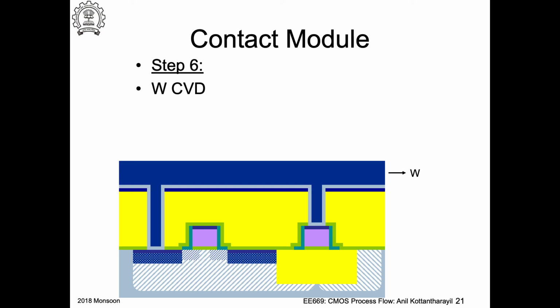So now you fill this contact regions using tungsten. So you deposit tungsten everywhere, right? Yeah. So this is shown very nice and clean, right? In the schematic. So you get tungsten. Okay. Then the next step is to CMP the tungsten, right? So chemical mechanical polishing is used for removing the tungsten. And then you also remove the titanium nitride barrier from the top oxide cap there, and the pre-metal dielectric. Pre-metal dielectric is phosphosilicate glass, right? Okay. So remove all of this.